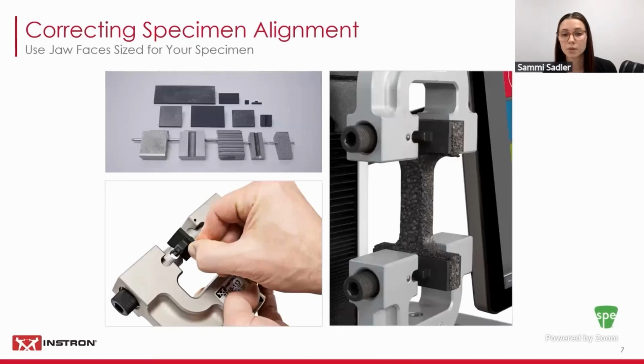Another thing that you can do is ensuring that your jaw faces are the same width as your material. So for example, with thin film testing, a lot of the time the width of a thin film is 25 millimeters. So it would be beneficial to have a jaw face that is also 25 millimeters wide. That way, when you're placing your material within the grips, you can see if it's overflowing on one side or the other to ensure specimen alignment.